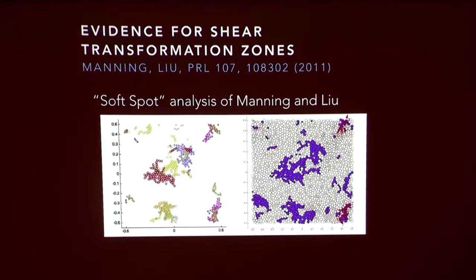Right. So I guess there's the question of rearrangement. Are the saddle points ubiquitous, and wherever you get pushed in a particular direction long enough, you'll find a saddle point? Or are the saddle points very special, and you may get pushed very far in a particular direction, but you just don't find a saddle point in that direction, and the fact that it's soft is really irrelevant, right? So here it seems to be indicating that there's some relevance to the local softness, but that it may not be enough to fully specify where the saddle points are. Right, no, but this is all at a very hand-waving level, I can explain this by saying that if I have a soft direction, when I apply external stress, the system will preferentially move in that direction. But that doesn't tell you that it'll necessarily undergo a plastic instability.